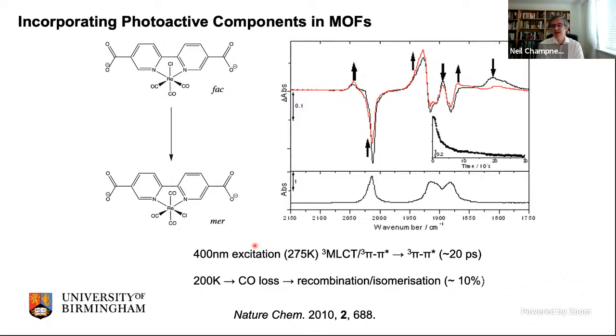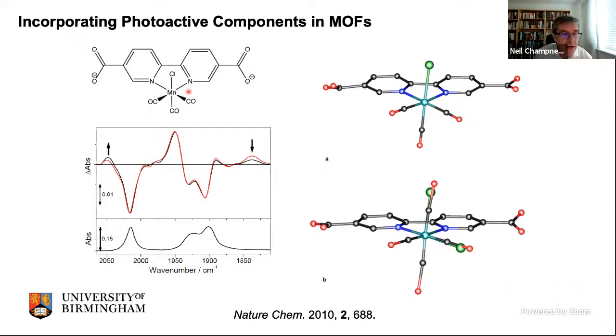And actually, 10% isn't very much. It could just be consistent with the first few layers of the surface of the crystal, in fact. It's quite possible that's about 10% of your crystal. And it's not enough for us to study this by single crystal X-ray diffraction. So we move to a related system. So we can make this analogous manganese complex here. So we now have a manganese tricarbonyl chloride BIP complex.